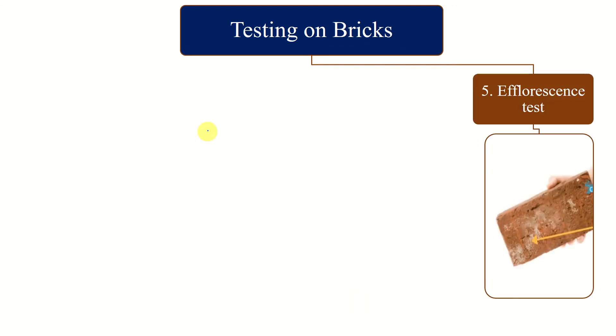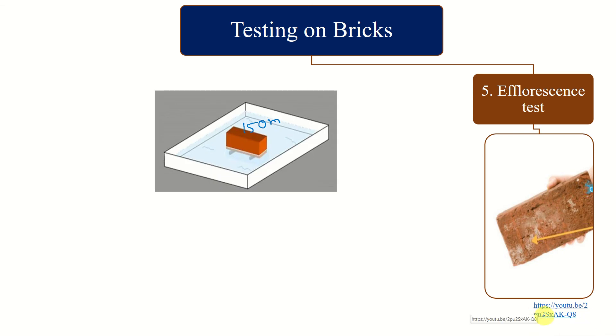Let us come to the last test, efflorescence test. The brick is placed in 150 mm diameter porcelain disc containing 25 mm depth of water at room temperature. You can see the brick is placed in water up to 25 mm depth. We have to leave it till the water is completely absorbed by this brick.